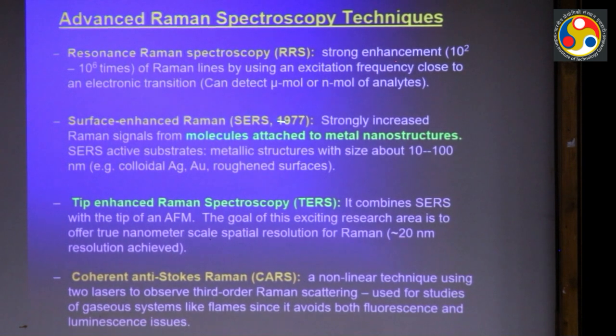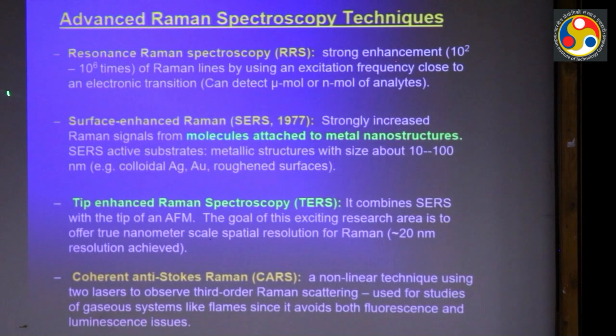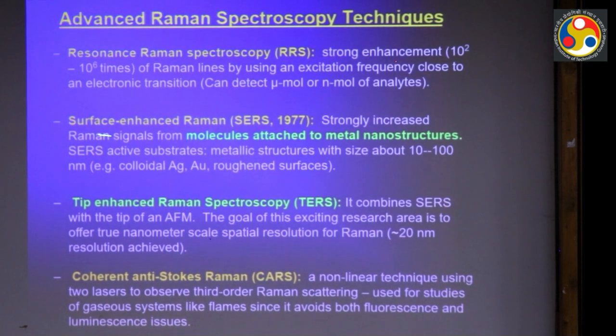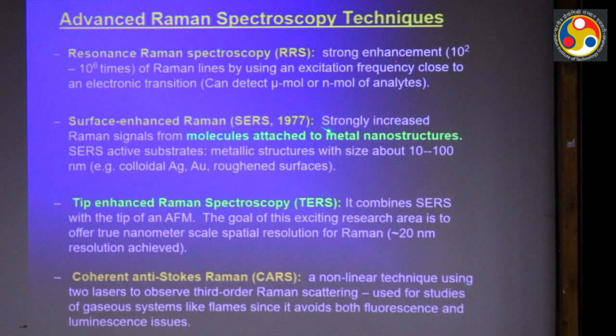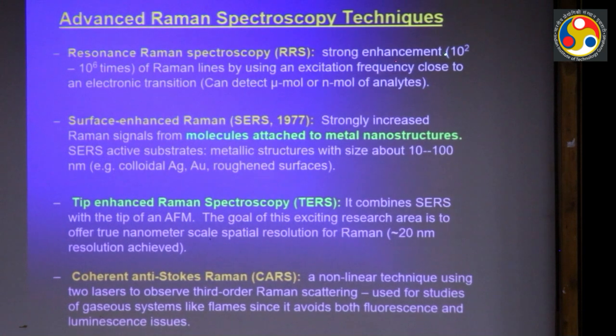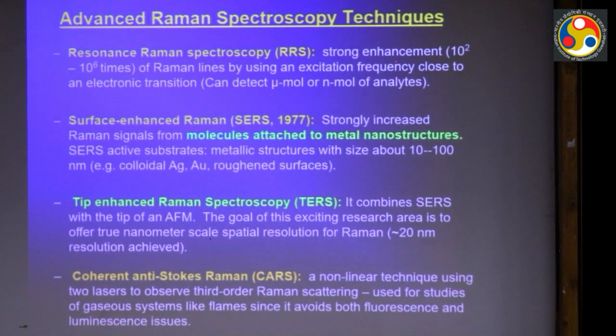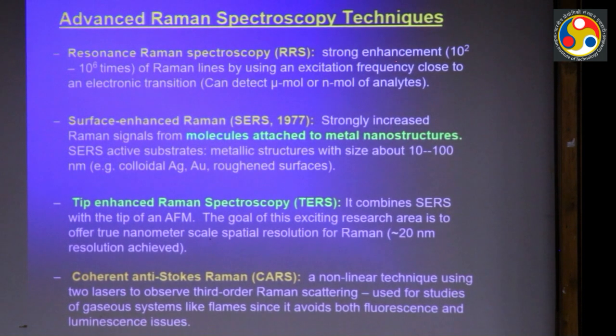Another technique which is very versatile, which everybody uses, biologists, chemists, physicists, is called surface enhanced Raman scattering, which was discovered way back in 1977, but still a lot of research is going on in this. Here you have about 10 to the power 2 enhancement, but there you can have an enhancement of the order of 10 to the power 8, meaning 100 million times enhancement of the Raman signal. This is remarkable. With this you can actually detect even a single molecule today using this surface enhanced or tip enhanced Raman spectroscopy.